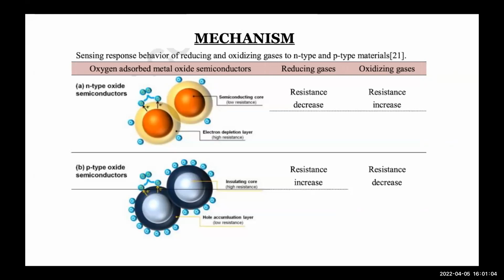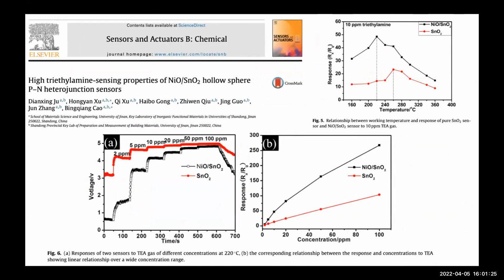In a P-type oxide semiconductor, we know that holes are high in concentration, so they form a hole accumulation layer which has a low resistance. And when a reducing gas is introduced, the resistance increases, and when an oxidizing gas is introduced, the resistance decreases. So now we come to the next part of our presentation, paper literature.